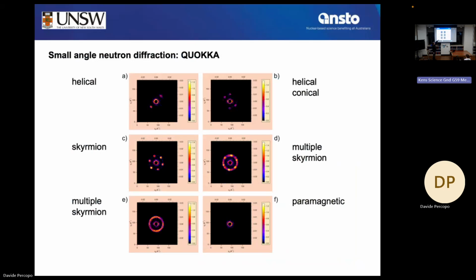Next picture, number B, also helical, but now we have two domains. And finally, the skyrmions have formed 6 sharp peaks, a hexagonal superstructure. They are quite wobbly. They can rotate, and in most cases, you end up with a ring structure. And paramagnetic means above the ordering temperature, to confirm that they disappear. It's always an important cross-check.